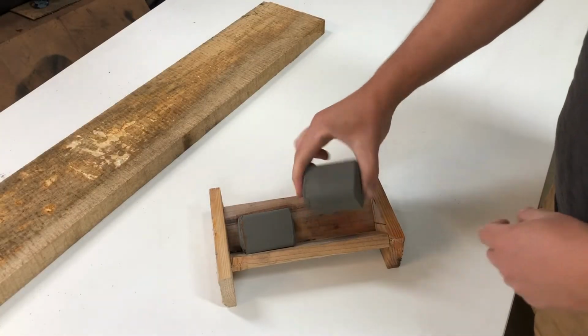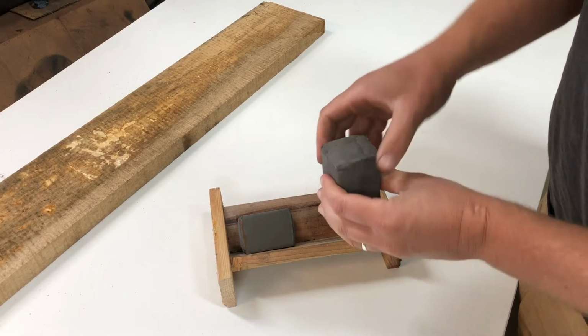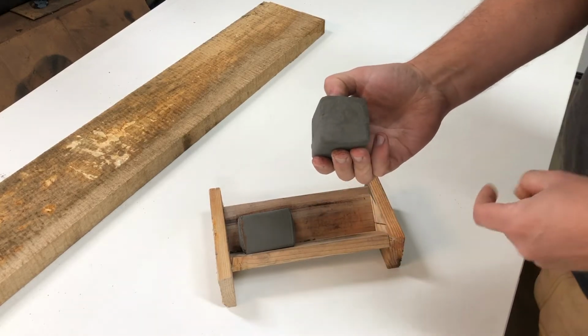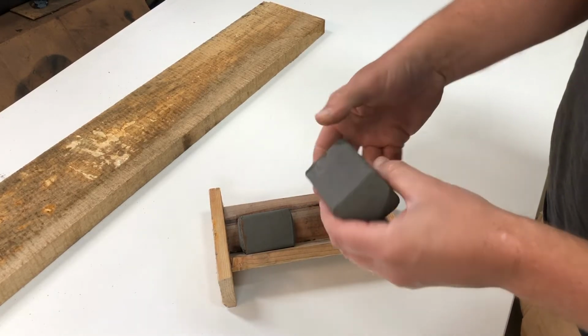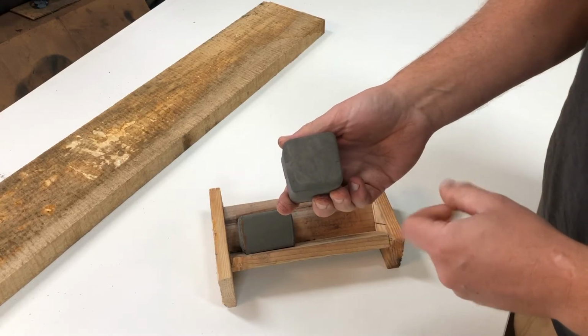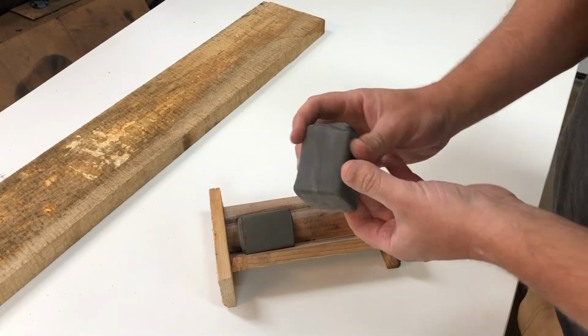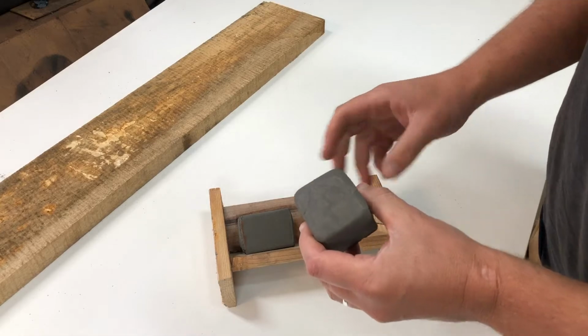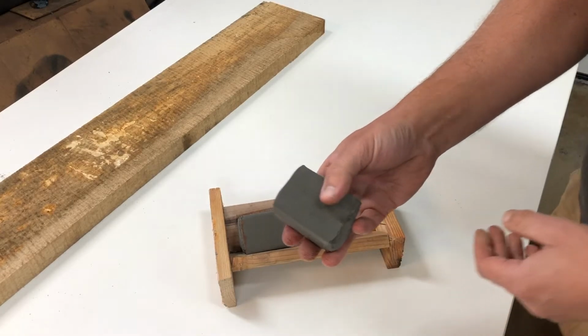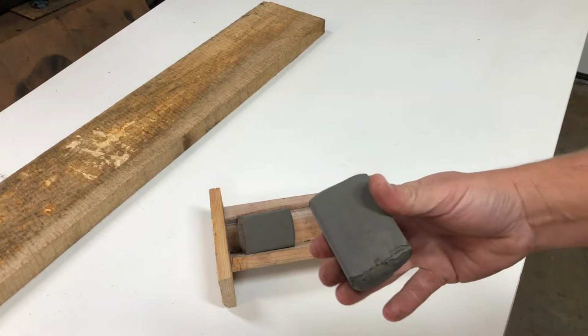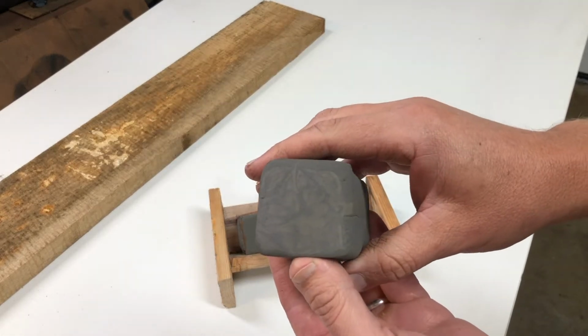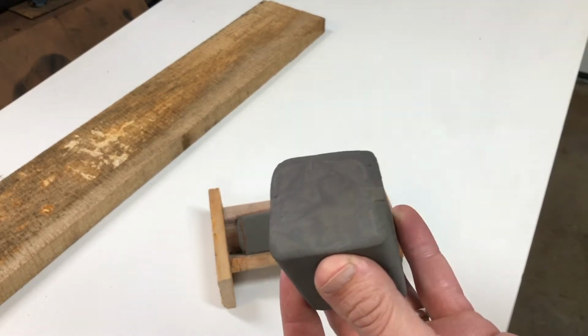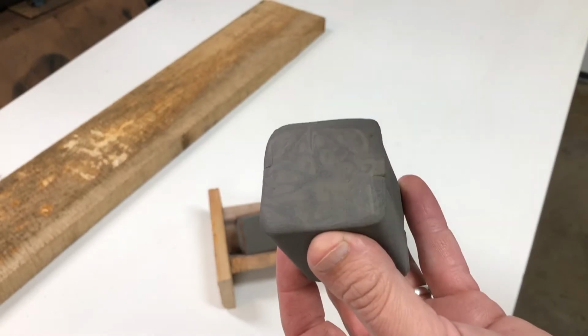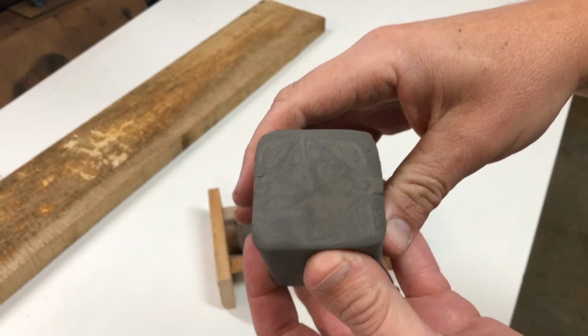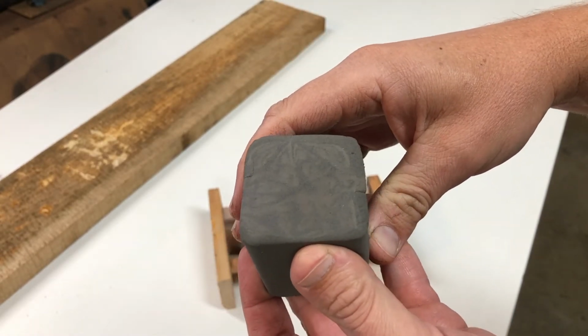So at this stage, these blocks have been in the kiln just at 110 degrees Fahrenheit for about 10 hours. And you can see they have firmed up nicely. Let's see if we can't get a little better view on the end here. Well, the light's just not quite good enough. You can see the pattern in there a little bit.